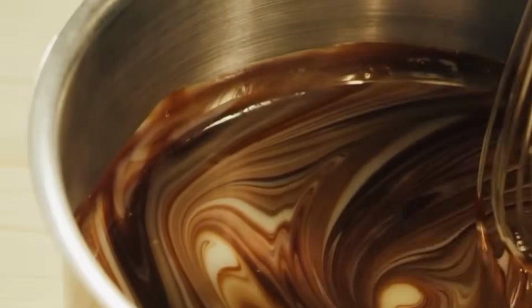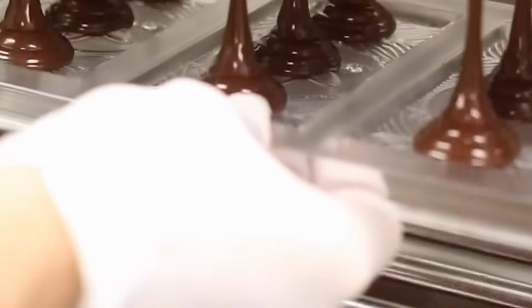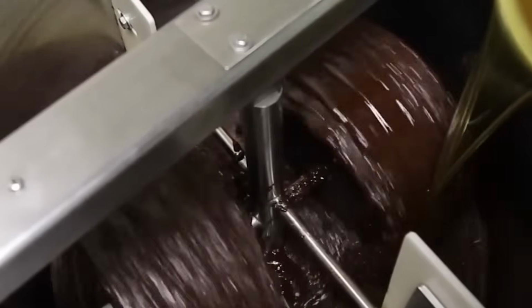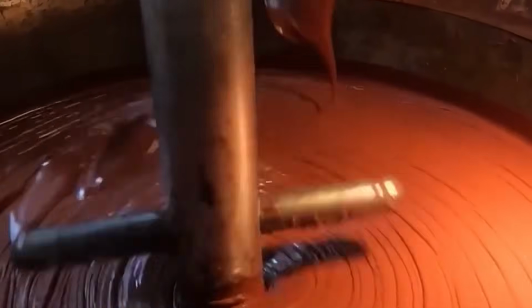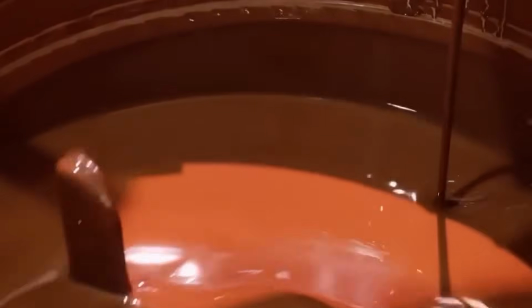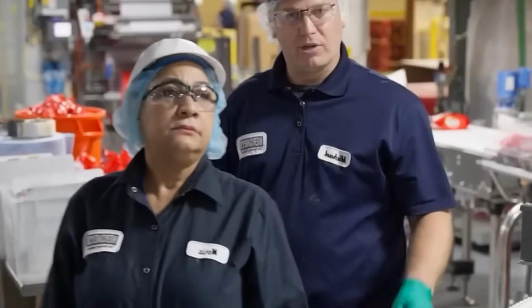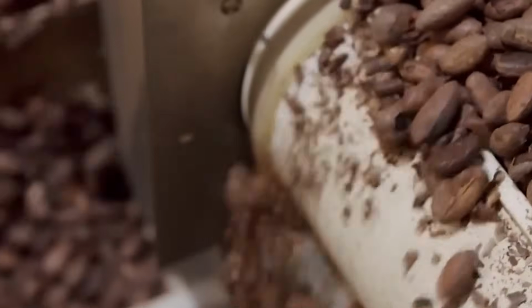The sugar crystals are still relatively large at this point, and the milk powder has not fully hydrated, so the mixture is lumpy and thick. But the goal of this step is to distribute the ingredients uniformly before refining. The refining process consists of passing the chocolate paste through a 5-roll mill or similar refining system, which crushes and shears the mixture repeatedly until all particles are reduced to between 15 and 20 microns in size, which is below the threshold of perception on the human tongue and is responsible for the smooth texture of finished chocolate.